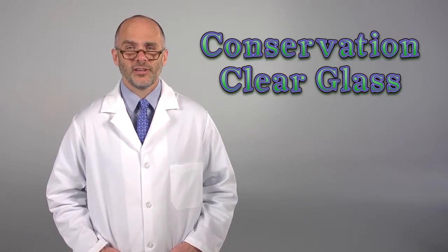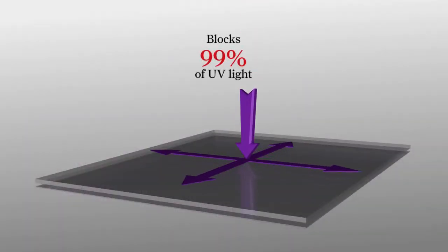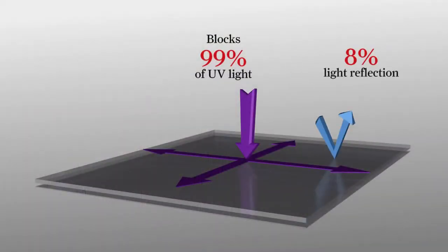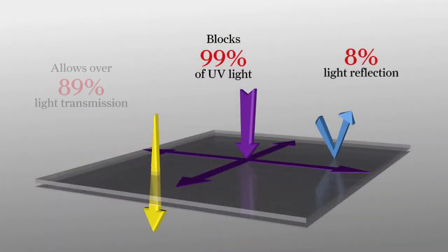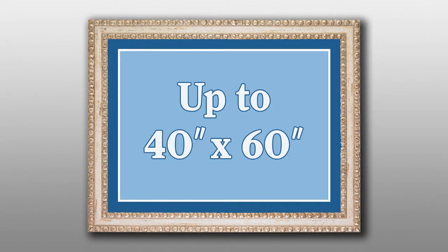Conservation Clear Glass is a standard option, providing 99% UV protection against damage and fading over time. Its ultraviolet filtering comes from a proprietary coating that is baked onto the side of the glass that faces the artwork. With only 8% of light being reflected and more than 89% of light transmitted, it is recommended for any framing application if reflection-free viewing is not important. This glass is available in sizes up to 40 by 60 inches.